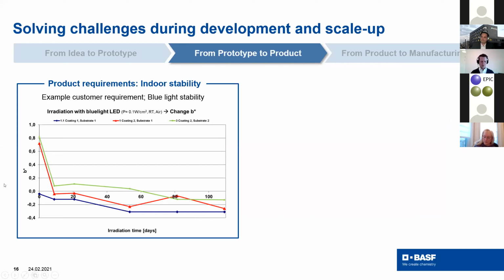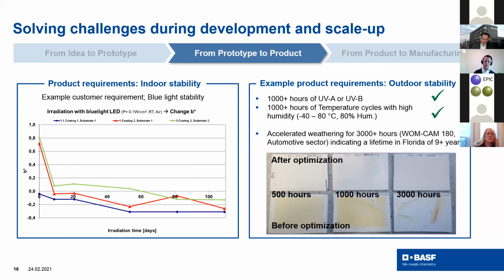So that's what we did here. We did more than 100 days of irradiation with a blue LED and show them, look, our B value, so that what comes for yellow, does not change over time that greatly and matches the specification of the customer. On the other side, we also have, not for this glare control foil, but also for other products,